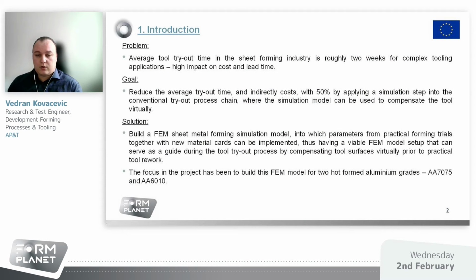Within the FormPlanet project, we investigated how to reduce the tryout time for tooling applications, as this is a costly procedure in the sheet forming industry. The goal was to implement a simulation step into the conventional tryout process in order to reduce the tryout time by 50%. The solution to this was to build a FEM sheet metal model into which parameters from practical forming trials along with new material cards were implemented. FEM models were built for two hot-formed high-strength aluminum grades, namely AA7075 and AA6010.